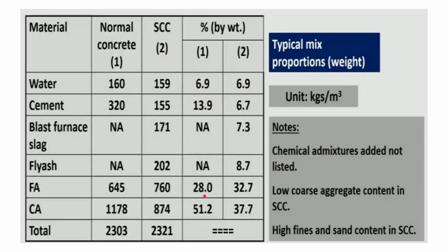As you can see here, we have the amount by percentage by weight of the individual constituents, with a comparison between normal concrete and self compacting concrete. By percentage of weight, the water is almost similar, around 7%. But in the case of cement, normal concrete has a higher concentration, almost 14% by weight, whereas in SCC it is around 7%.